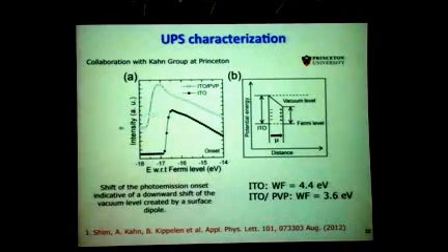We were wondering what was going on, so we sent these materials to Antoine Kahn at Princeton, who did some UV photoemission spectroscopy. You can see from the shift in the onset of the secondary electrons in the UPS experiments that there's a downward shift of the vacuum level, due to the formation of a surface dipole through the physisorption of these polymers onto the surface of the ITO.